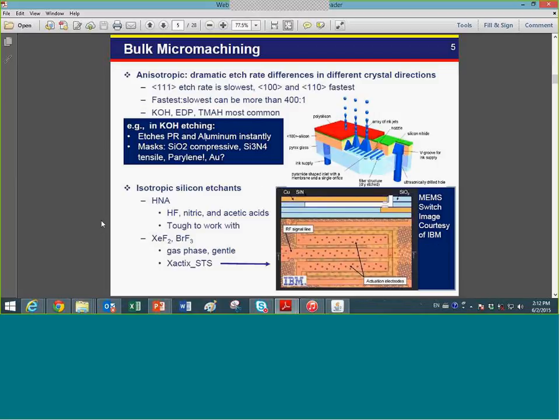I will talk about maybe three typical subtractive processes for making patterns in materials by etching. The first is bulk micromachining. Bulk micromachining involves etching to remove the silicon material. Because the etching rate is strongly dependent on the single crystal plane, the anisotropic etching of silicon can be done using KOH, EDP or TMAH, which is a CMOS compatible etchant. In typical applications, you can build up many kinds of geometric structures on the silicon.